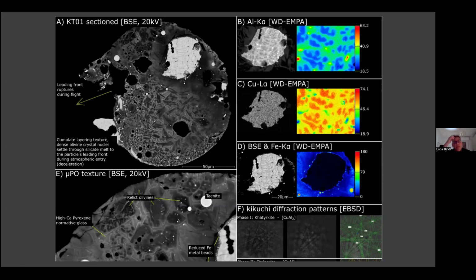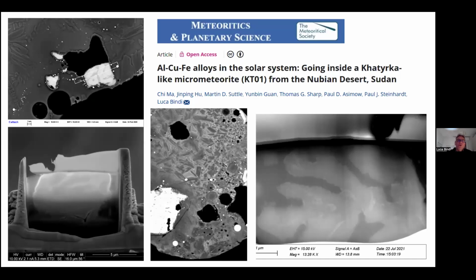Well, I was able to get this very precious micrometeorite from these British guys, and together with our research group, we carried out a new study. I mean, a focused ion beam transmission electron microscopy study to study the interface between the copper aluminum alloys and the silicates. You can see here the FIB lamella we were able to collect in this TEM study.